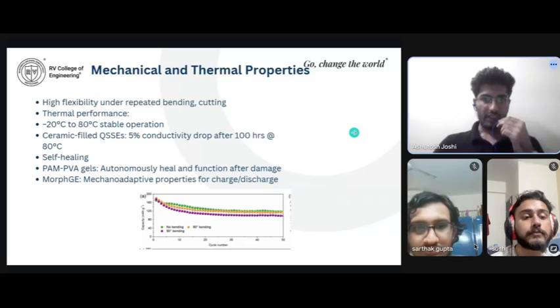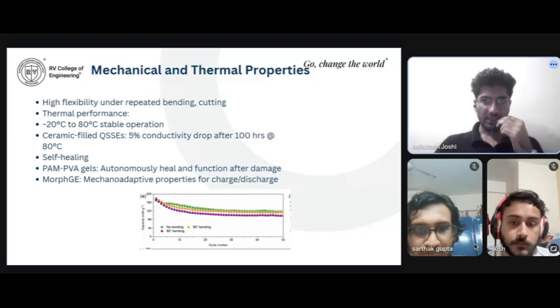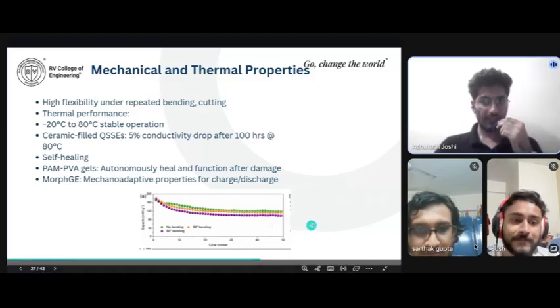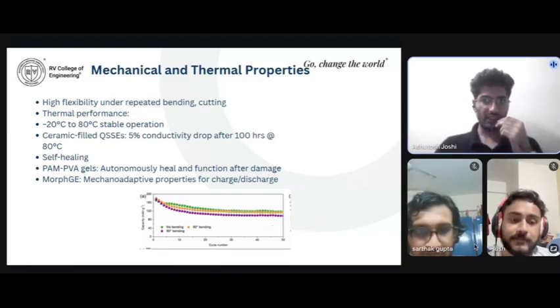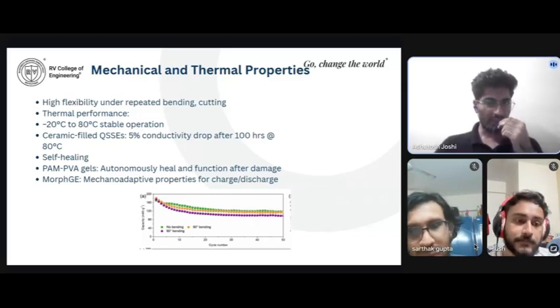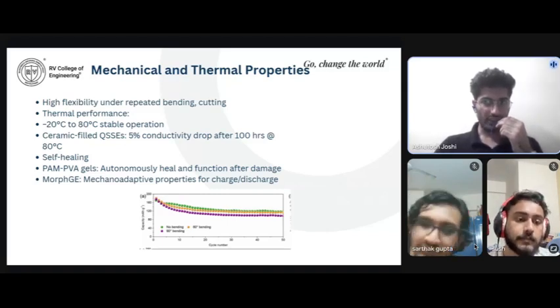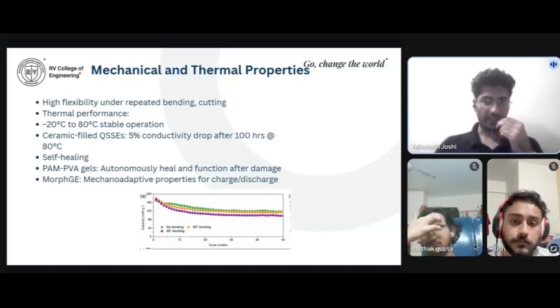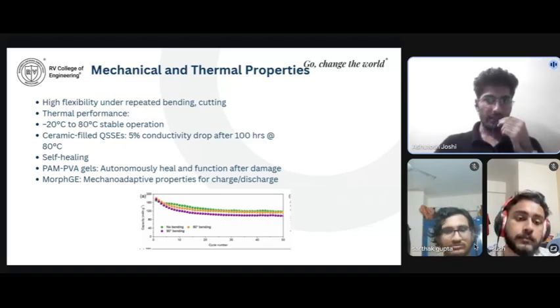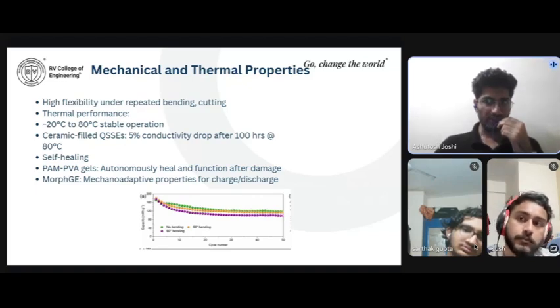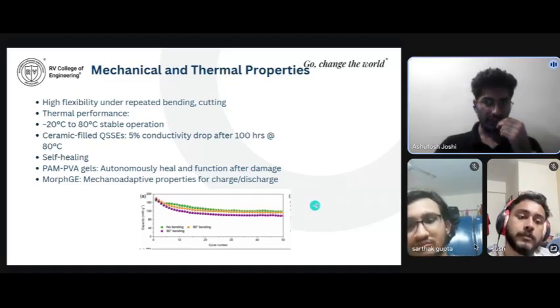The graph here represents an examination of the mechanical flexibility of a QSS under different bending conditions. Here, the y-axis again shows the capacity, and the x-axis shows the number of cycles up to 50. Different colors represent different bending angles: green for non-bending, orange for 60-degree bending, and purple for 90-degree bending. What is interpreted is that the three curves begin with similar capacities. However, as the bending angle increases, the drop in performance is slightly more notable. Even at 90-degree bending, the battery maintains a capacity above 180 after 50 cycles.